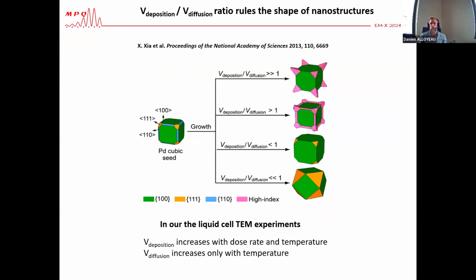The other thing we have been able to show in this temperature control experiment is the possibility to visualize the whole nanophase diagram of nanoparticles. And this nanophase diagram really depends on this competition between deposition rate and diffusion rate. And we have been able to confirm a theory proposed by Professor Xia at Georgia Tech University,